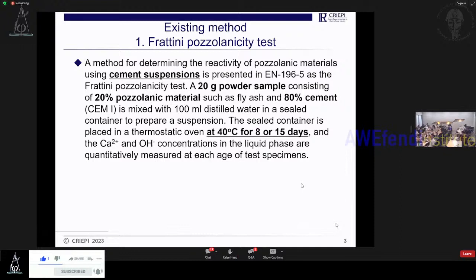There are already a few testing methods. Firstly, it's named the Frattini pozzolanicity test. It also uses cement suspensions, and the suspension is made from 20 grams of powder samples, 20% is pozzolanic material like fly ash, and the other 80% is cement. The reacting condition is 40 centigrade, kept for 15 days.